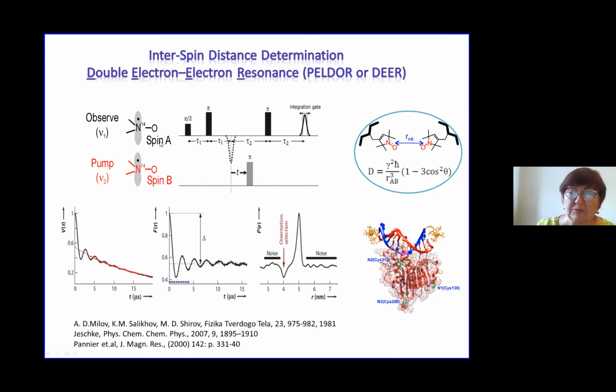The idea is as follows. If we have 2 spins, spin A and spin B, and they are coupled by dipole-dipole interaction, then we are looking at the intensity of the spin echo of observed spin A. Then, if during the time of evolution we apply an additional pi pulse, we change the orientation of spin B, that means the sign of the dipole-dipole interaction. And then we are looking at the intensity of the spin echo. As a result, we see something like that. It is decaying oscillations. Then by subtracting the baseline and taking this oscillation, I have no time to explain in detail, but one can get this dipole-dipole interaction. And as dipole-dipole interaction is coupled to distance between molecules, one can get information about the distance between two radicals.